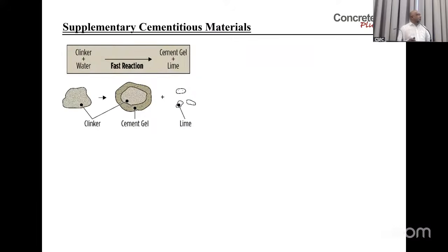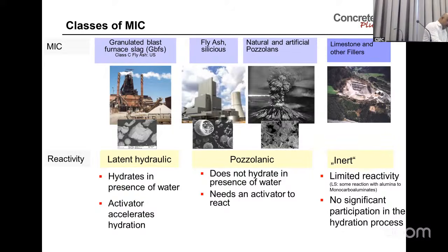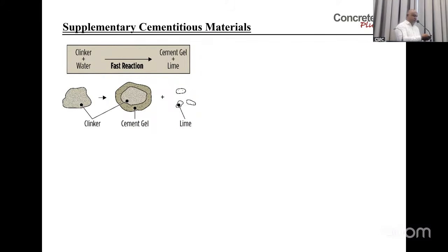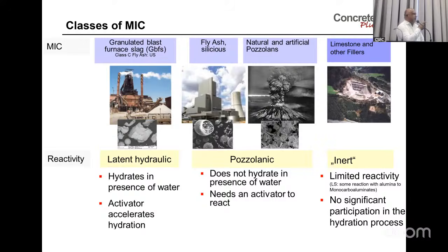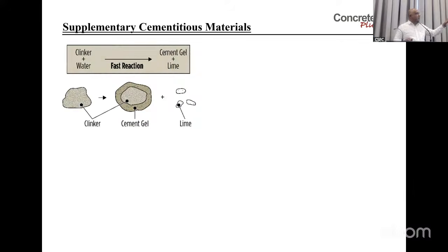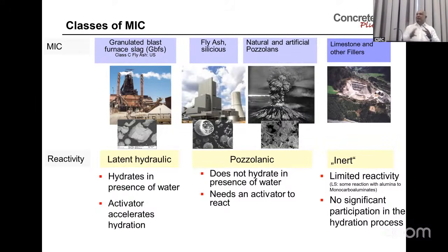That's the second thing. So if you see here, the first one is slag. What you see from the scanning electron microscope, enlarged, is like aggregate. The second one, fly ash, as I mentioned, is spherical. So if you go further, when you add slag into your concrete, workability will go down drastically. But if you add fly ash into your concrete, because of the spherical shape, it enhances your workability. That's why wherever you need more workability, fly ash is highly recommended.